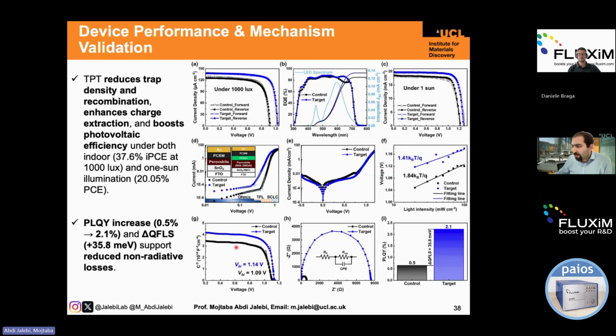And here is the impedance measurement. As you can see, we have significantly higher recombination resistance for the target sample and lower series resistance for the target sample as well. And the built-in potential is higher for the target sample as well. So it's 1.14 volt versus 1.09. So this is overall showing that we have reduced the trap density and recombination, and we enhance the charge extraction, which all in all helps us to boost the performance of the solar cell in both indoor and also one sun condition. And lastly, the PLQE of the devices shows that for the target it is over 2% versus 0.5% for the control sample. So this also supports the reduction in the non-radiative recombination.